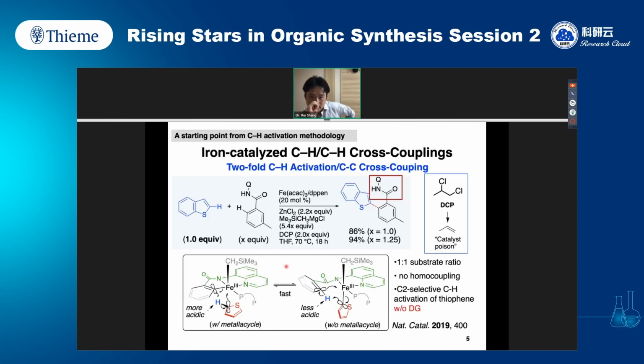Why did we start this research? The starting point for making conductive polymers using iron-catalyzed CH activation came from our methodology study on iron-catalyzed CH-CH coupling. In 2019, we reported the first twofold CH activation cross-coupling using just a 1-to-1 ratio of the CH substrates. The reaction achieved exclusive selectivity for cross-coupling, with no homo-coupling observed. We used a very mild 1,2-dichloropropane as a terminal oxidant to turn over the iron catalyst, and the reaction is specific to the C2 position. We didn't observe any activation of the C3 CH bond on thiophene.